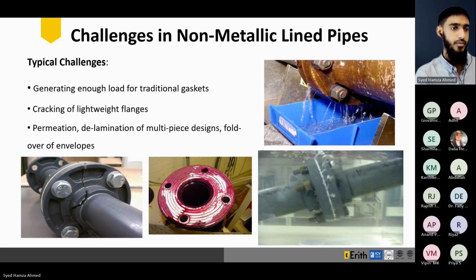Now talking about challenges faced in our non-metallic lined pipes. Basically, in non-metallic lined pipes, the major hurdle that we face is creating and generating enough load for traditional gaskets. Traditional gaskets require higher bolting loads and higher gasket stresses. That is very difficult to do with non-metallic pipes due to their reduced strength. And if we do use the common gaskets, maybe aramid-type gaskets or other gaskets, they can cause cracking of the lightweight flanges, whether it be FRP or GRE.